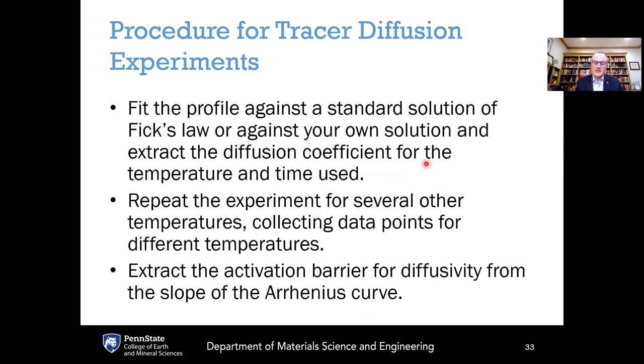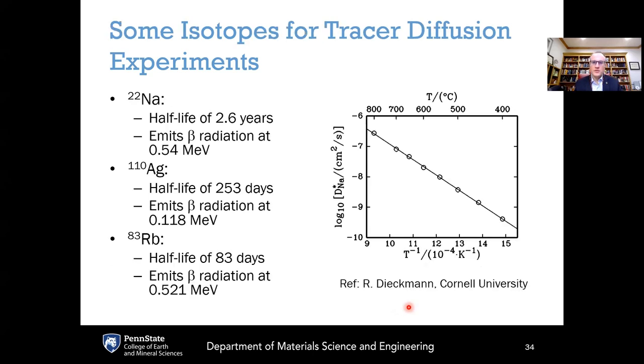Then you fit that concentration profile against a standard solution of the diffusion equation, which is what we're going to cover in the next chapter, chapter 4. Repeat the experiment for several other temperatures, and then having the diffusion coefficient as a function of temperature, if you plot the logarithm of the diffusivity versus 1/temperature, that gives you the Arrhenius curve for the tracer diffusion experiment.